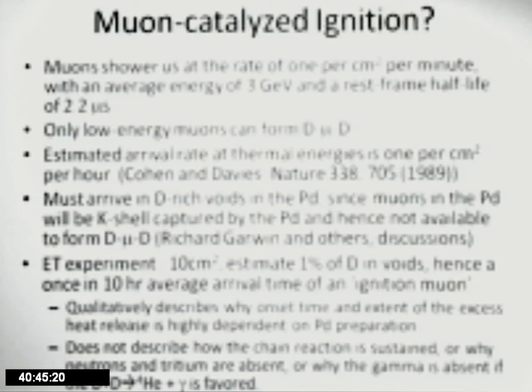Let's see. It's interesting because this muon catalysis argument works out roughly right for describing the long onset times of the excess heat release, but it does not describe how the chain reaction is sustained, or why neutrons and tritium are absent, or why the gamma is absent if the D plus D going to helium-4 plus gamma, which only occurs one time in a million of these reactions in free space, is somehow favored in the salt. So there are a lot of things that make the concept of the muon catalyzed ignition process being responsible for this suspect.